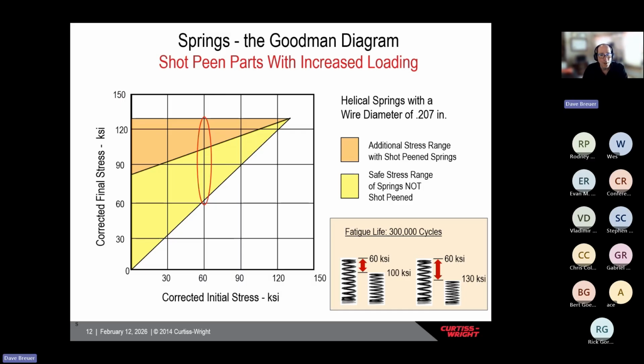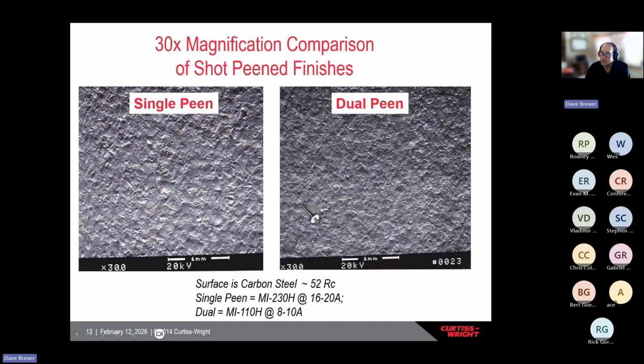Most of what we do is a single peen. This thing here is a 230H, which is a very common shot - a 23 thousandths diameter hardened steel shot at 16 to 20 thousandths A. That's this left one here. This is a 30x magnification, which is pretty good size magnification. You can see the individual peening dimples.